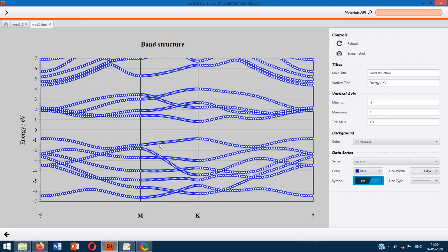Today, as I have input more number of points for each segment of the Brillouin zone sampling, that is the gamma M K gamma path, for each segment I have 50 points. So this structure looks much denser in the number of points, and that is the right kind of thing to do. And we can observe that this material, unlike graphene, has a band gap. It is around 1.7, 1.8 electron volts is the band gap in standard references for MoS2. So it is not giving a bad band structure, it's quite acceptable.